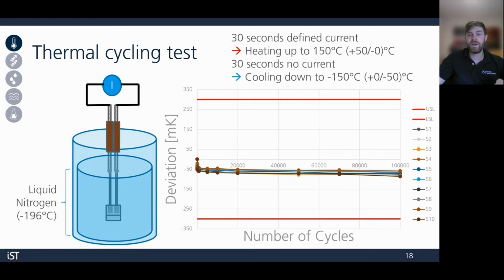So the way we do this is in 30 seconds, the sensor is heated up to 150 C or higher. This is done by sensor self-heating. So we drive a pretty high current through the sensor to heat it up. Then over 30 seconds, we apply no current and we let it cool to negative 150 C or below using liquid nitrogen. And this is repeated 70,000 times, and it's checked after several cycle counts. So here we have 20,000, 50,000, 70,000, and we even take it a step further to 100,000 cycles. And again, we see there's very little drift.